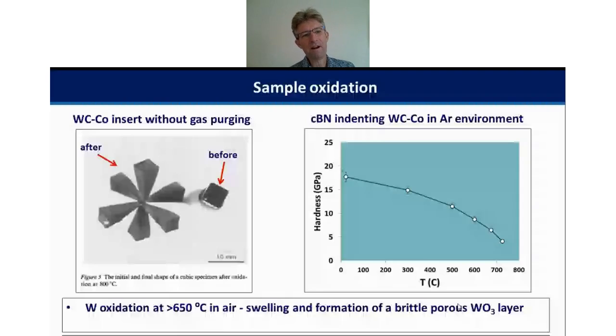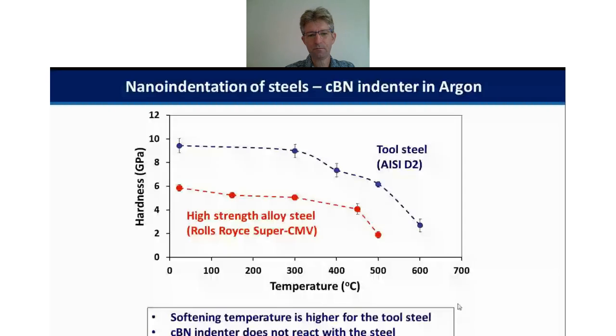So one way around this is to test in an argon environment, and in this case this is a cubic boron nitride indenter. This is some work from Lund University in Sweden. Again, you can see quite happily that in this case the error bars are actually slightly better at high temperature than at room temperature. So you have no problems at all in this case. Up to about 700, 725 is probably the limit for that application. So this combination of using a hard cubic boron nitride indenter and an argon purged gas environment is quite successful at testing a wide range of other materials as well.